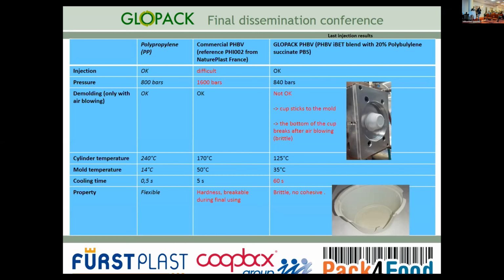Temperature is lower too, as explained, Hélène, it's normal. But cooling time is very high, 60 seconds. And finally, it is very brittle and not cohesive at all, because crystallization during cooling is very high.